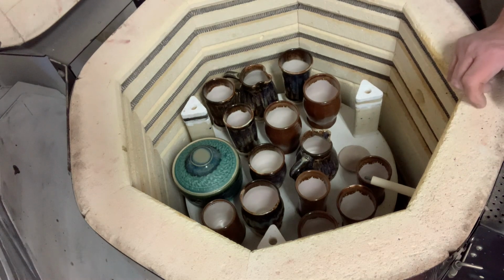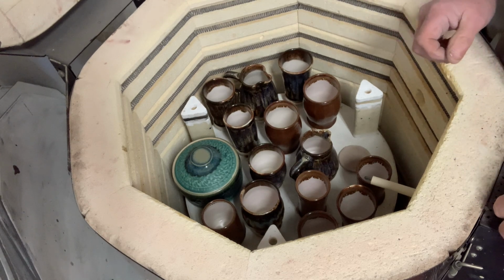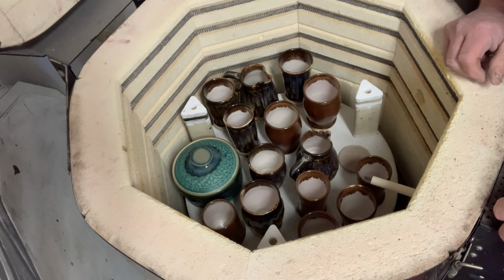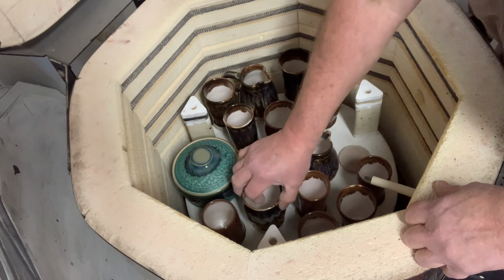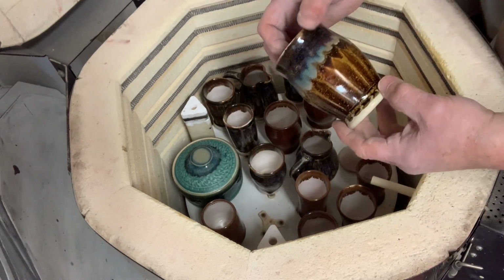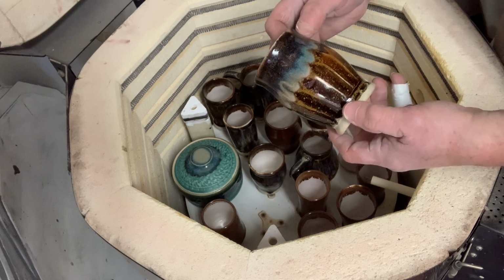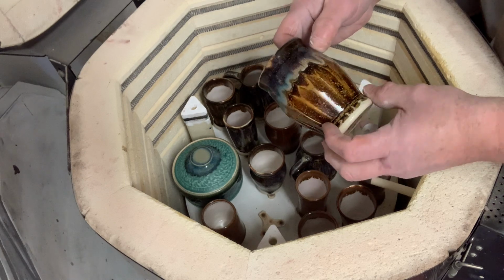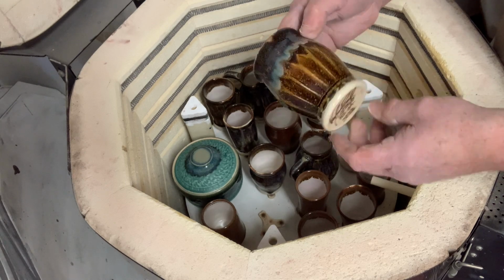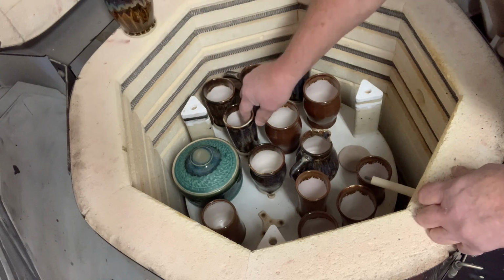Okay, this is the kiln. It's cooled down a bit faster than I thought. This one is the last of the firings of all the Tenmoku that I have, except for Ohata. I didn't use that one. But I'd increased the soak on this one at 1750 to 45 minutes. And it really did help by the look of it, because I think this is a better firing than the other one. That one, the iPad didn't record everything, but this one, here you go, that looks great.